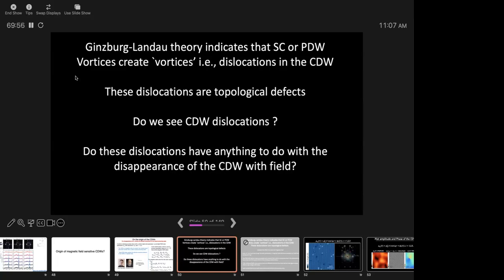According to the Ginzburg-Landau theory, the way the CDW disappears should be the following. When you turn on a magnetic field, you get vortices of both the homogeneous component as well as the pair density wave. And what Eduardo and Julian were able to show is that if you have isolated vortices of the pair density wave, then at those locations, the charge density wave should develop a dislocation, where the phase of the charge density wave should wind in real space by 2 pi.